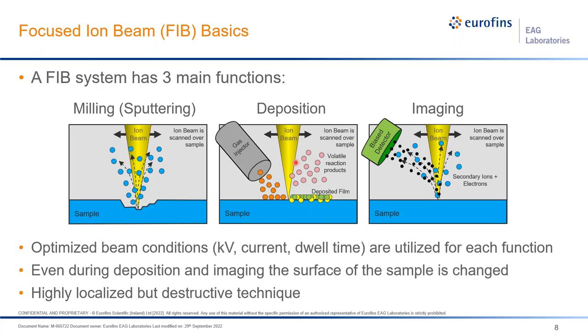So the FIB system has three main functions that we routinely utilize in the work we do. You have milling or sputtering, we have deposition, and then we also have imaging. So for milling and sputtering, this is the result of a series of elastic collisions where the momentum is transferred from the incident ion to the sample atom within a collision cascade region, and then they're removed from this targeted region of the sample. So we have the ion beam here, and the result is removal of material.